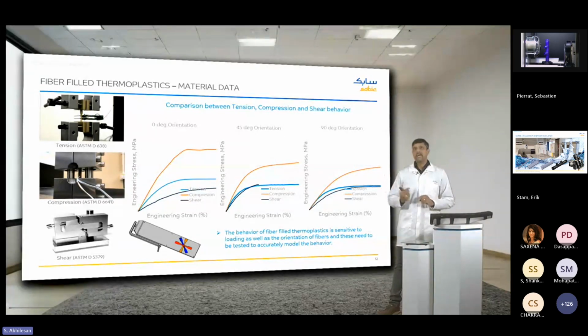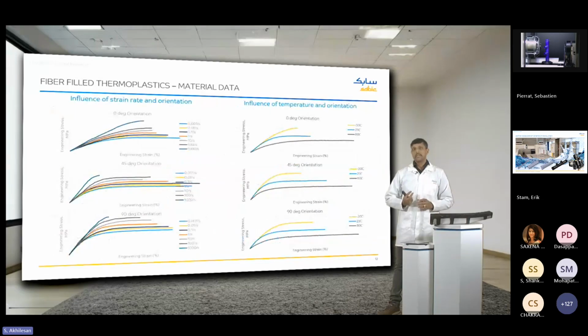So as you can see in the graph, when you take a real world example part like this, different regions in the part can have different loading states. Some of the regions could be in a state of shear, some of the regions could be in a state of compression. So we need to understand the behavior as a function of orientation as well as a function of the type of loading. And that again, we use specific geometries and test standards to characterize them as you see here. Once you have done this careful investigation, we then go into more advanced sensitivities.